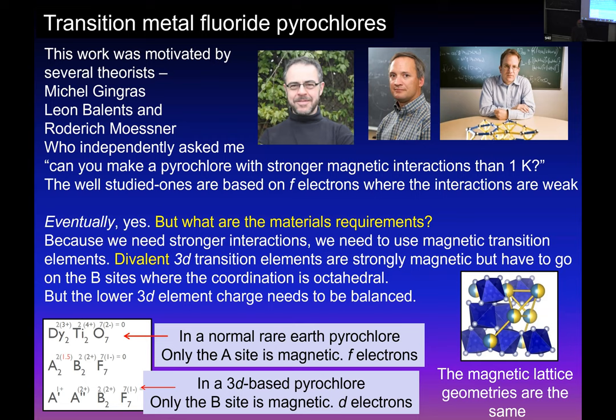If I want to have unpaired spins, titanium 4+ has no spin. Your TiO2, which you use every day in your life, is titanium 4+. It gave up all its d electrons to oxygen, and it's white, so you use it in paint all the time. So this is probably TiO2 everywhere. Good not to be allergic to TiO2. So anyway, there it is. TiO2 is not magnetic, so all the magnetism comes from the rare earth.